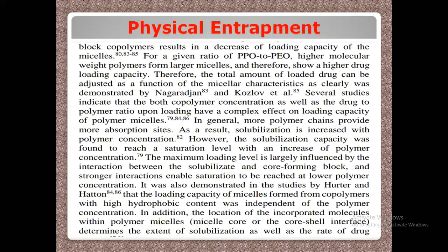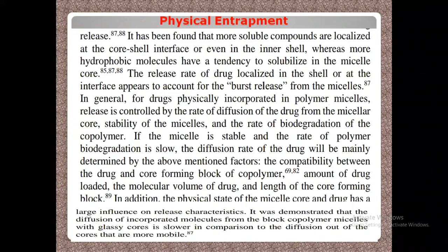And stronger interactions enable this particular saturation of the drug to be reached at lower polymer concentration. It was also demonstrated in studies by another group of people that the loading capacity of micelles formed from copolymers with high hydrophobic content was independent of the polymer concentration. In addition, the location of the incorporated molecules within polymer micelles, the micelle core or the core-shell interface, determines the extent of solubilization as well as the rate of drug release.